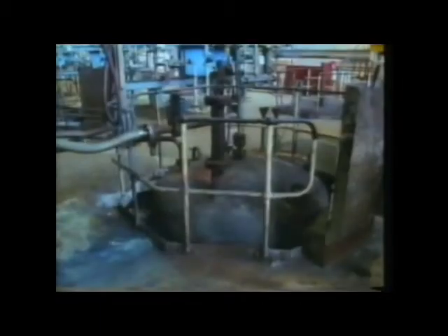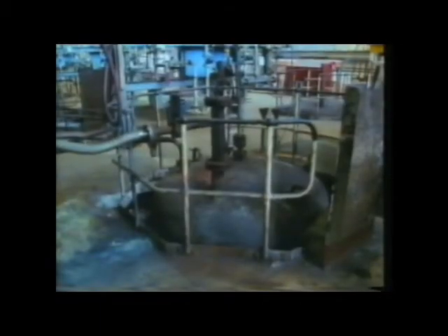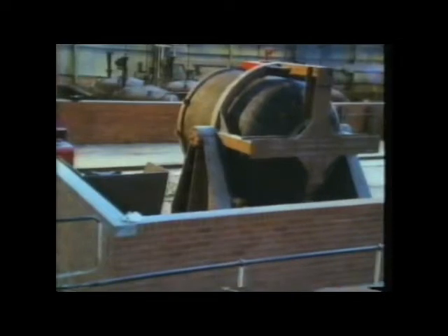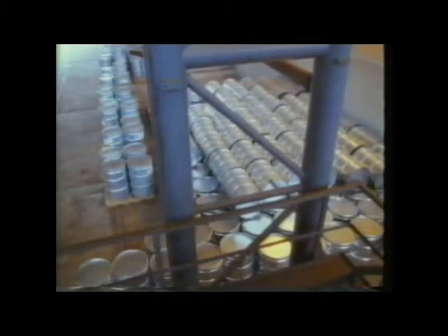Now the reaction vessel's heated for 36 hours. It's allowed to cool, then opened. Inside, there's solid salt, sodium chloride, coloured by the presence of traces of titanium compounds, and dark-coloured titanium metal. The salt's dissolved in water, and the titanium is filtered off and dried. Then it's packed for delivery to customers.